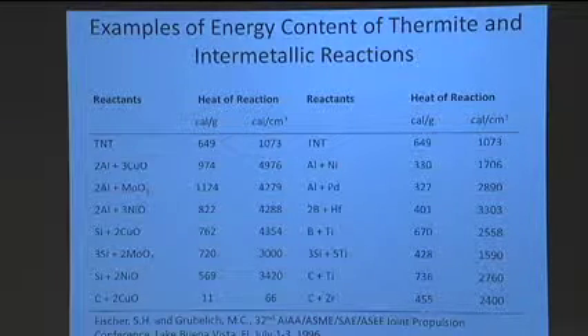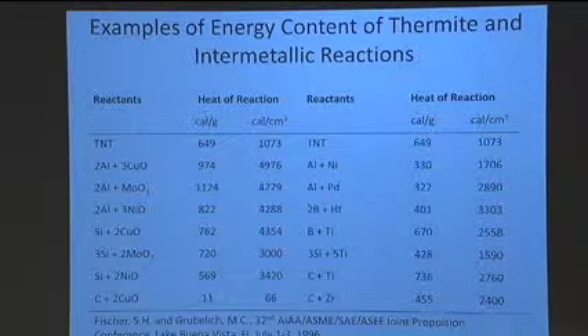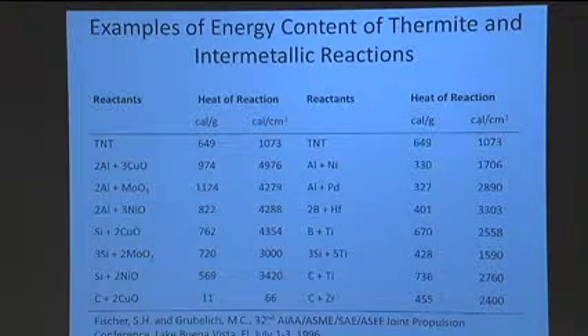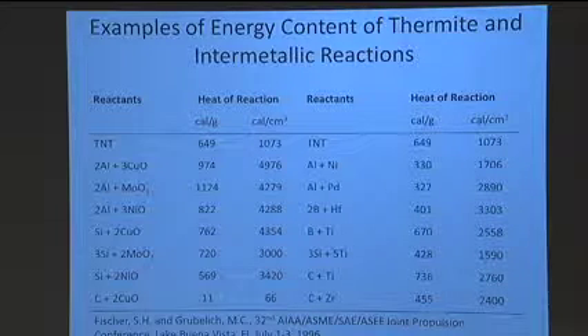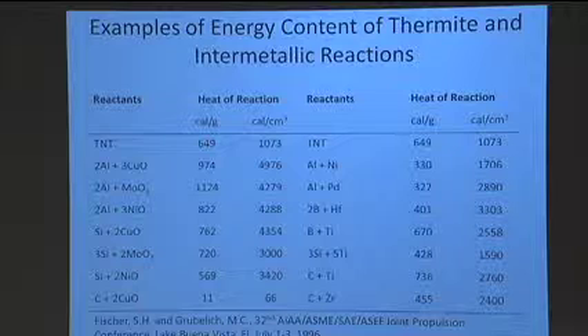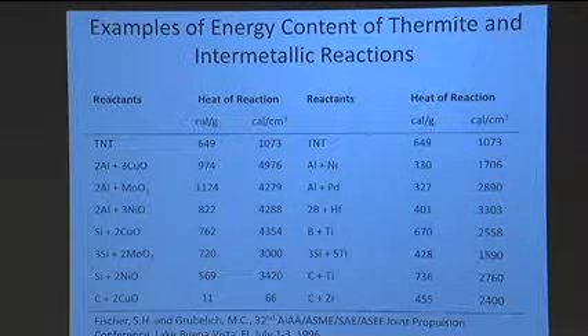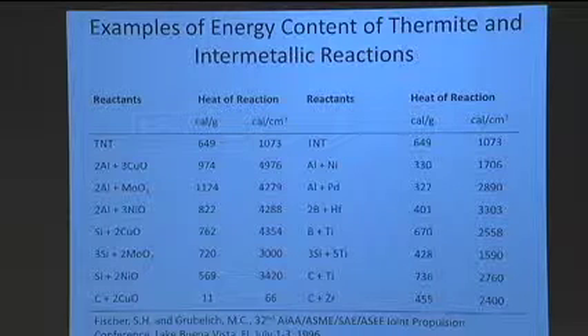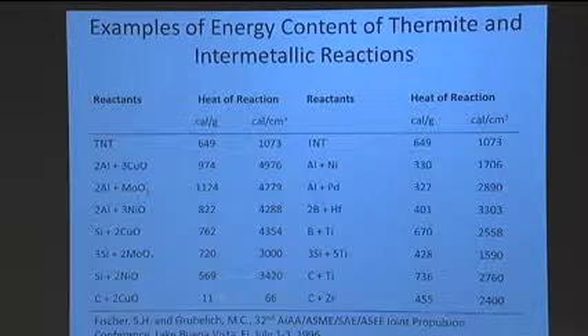If you look at the most energetic organic material, it's probably no more than a factor of 2 more than TNT. So if I compare it to some of these systems, you can see, on a gravimetric basis, easily comparable, but even more so on a volumetric basis, these intermetallic or thermite reactions are quite significant, even with silicon reacting with the components. And the intermetallics, same sort of result.